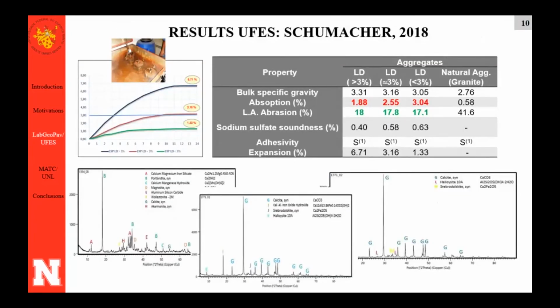So going now for the results of the two projects that we do in Brazil that are very related to the tests that I could do here in UNL. Let's talk again about the project that evaluates the effect of steel slag expansion. For that project, we took a sample of slags from the steel industry as is, without curing. This batch of slags that we brought has an initial level of expansion very high, 6.71. And we separated this big batch in 3 groups. So the first group we characterize as is, with no curing. And the second and third group we cure in laboratory to reach lower levels of expansion.